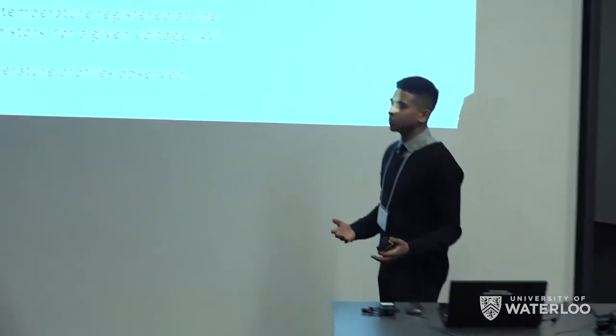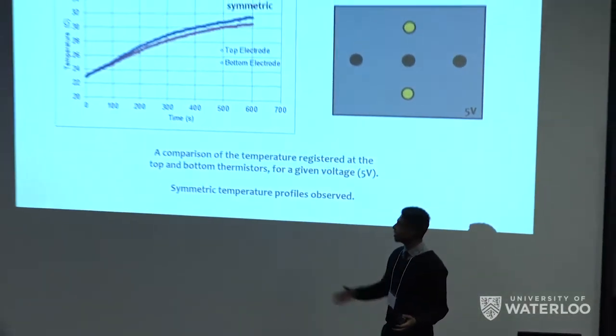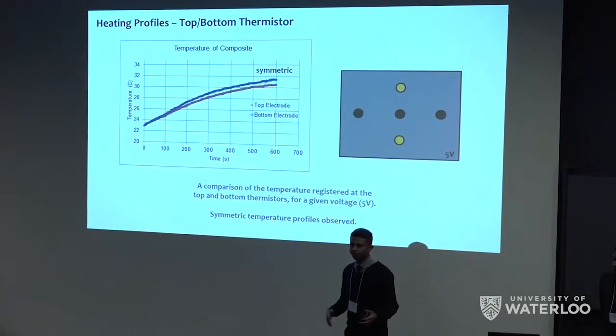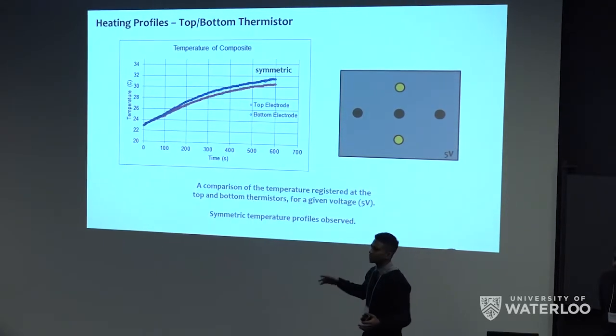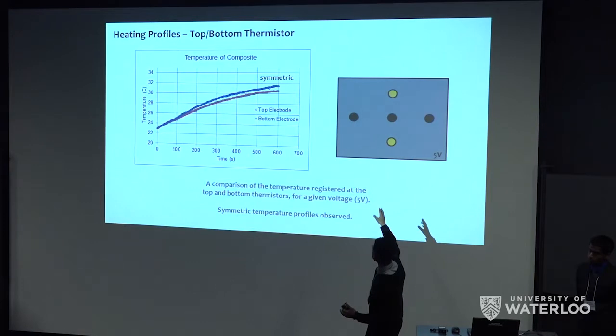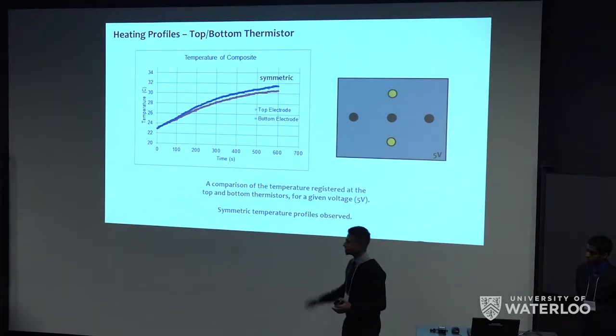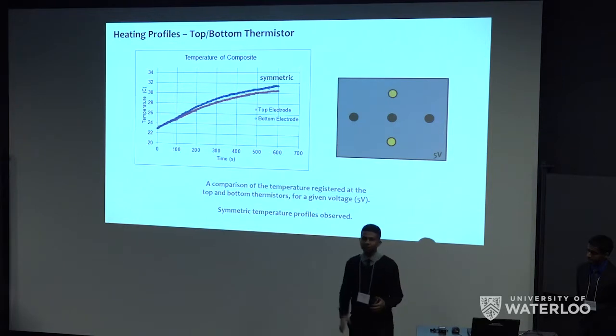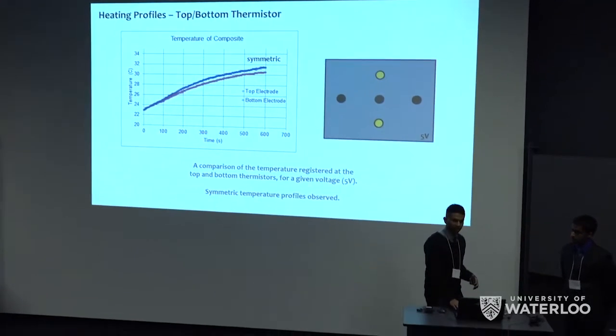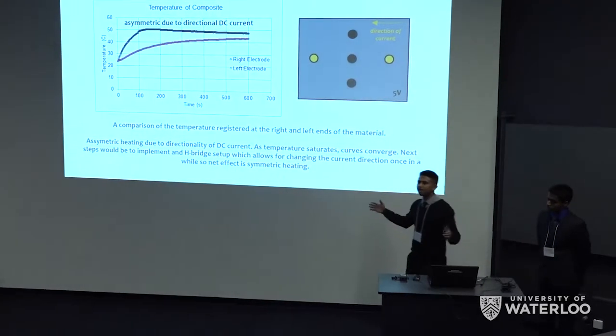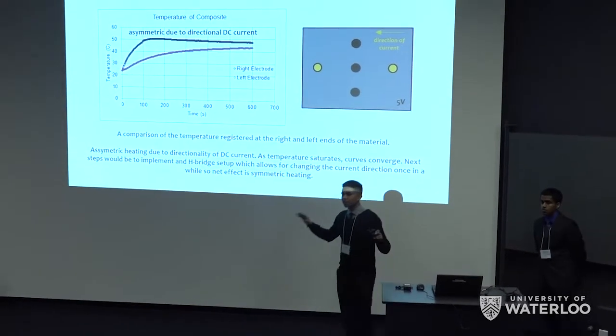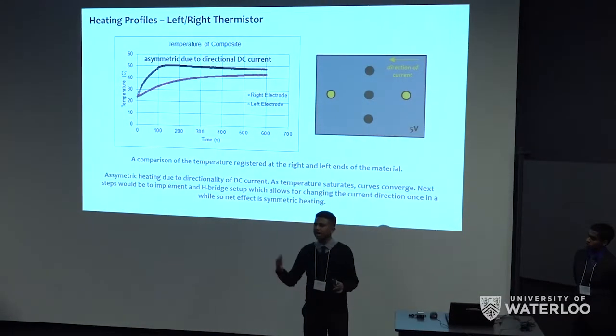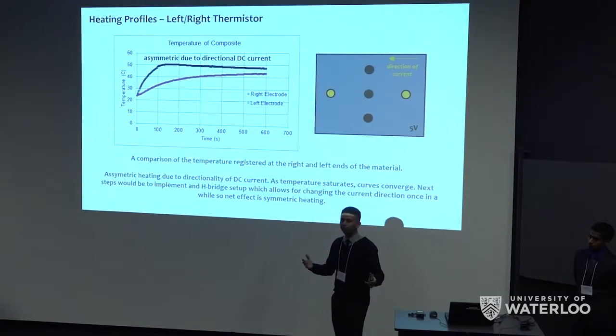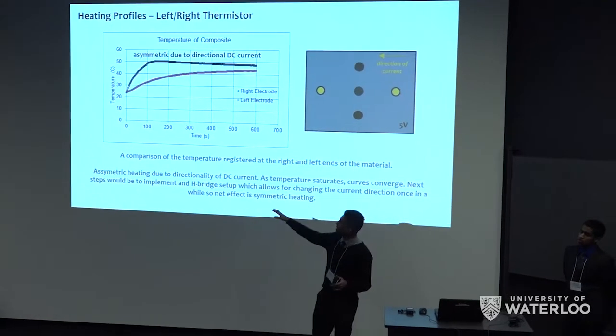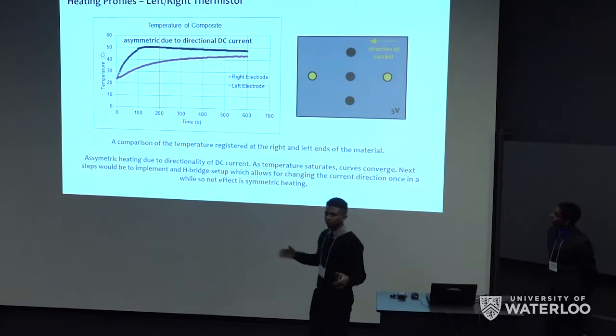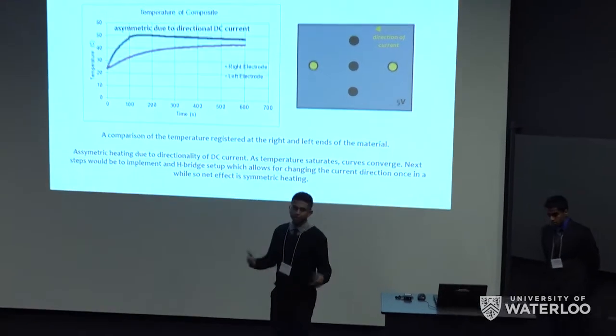Next, we really wanted to explore uniformity inside the material. So we have about 5 thermistors embedded in our polymer. And so what we wanted to see was to make sure that we were getting uniform results throughout. So here we have 2 thermistors at the top and bottom. And we see pretty symmetric results where they're reading fairly similar temperatures. But the real problem arises when we investigate different ends of the material, where we're placing thermistors at opposite electrodes. And because of how the voltage is dropping, we're going to notice significant variations in temperature initially. As time progresses, they will equilibrate to somewhat of a similar temperature, but it's still an issue in the beginning.